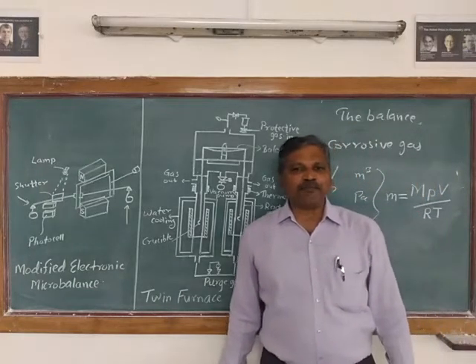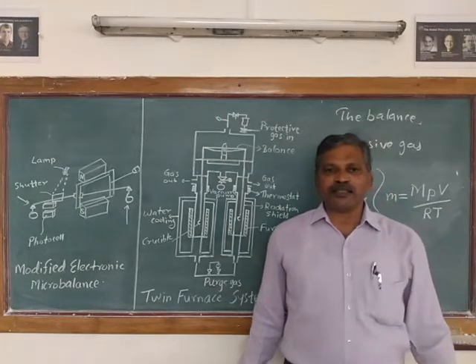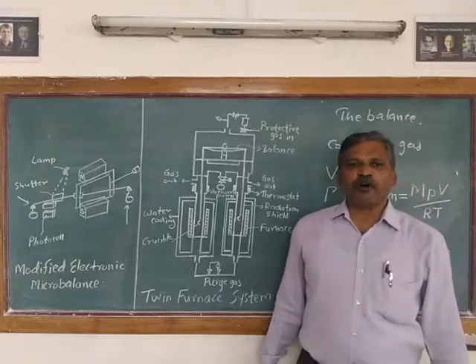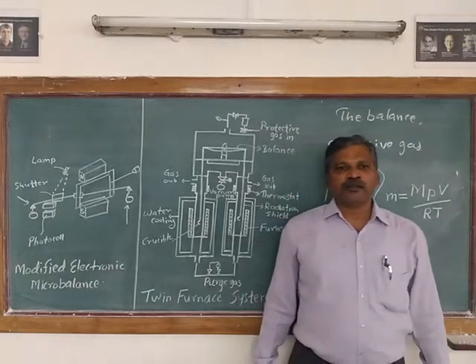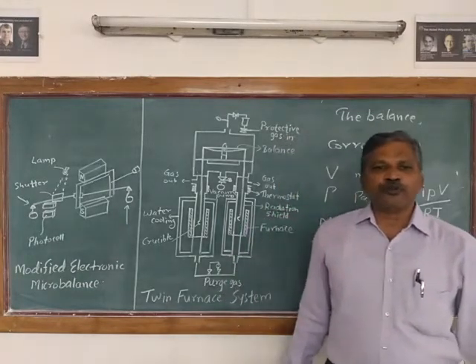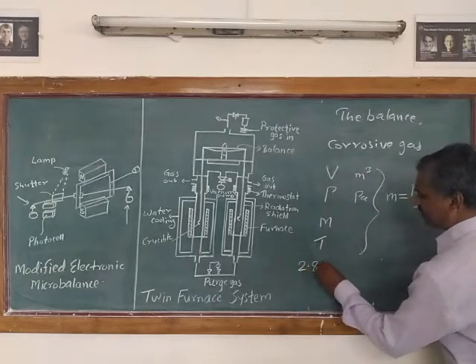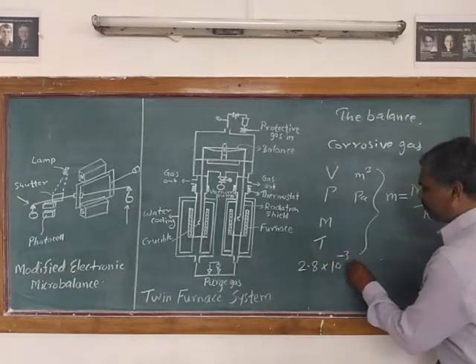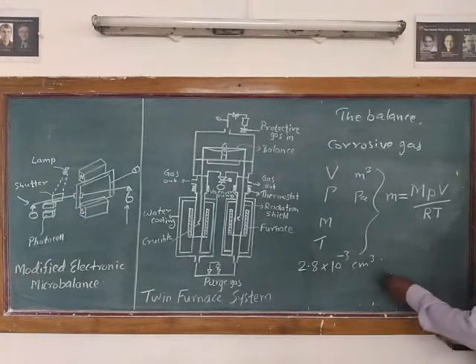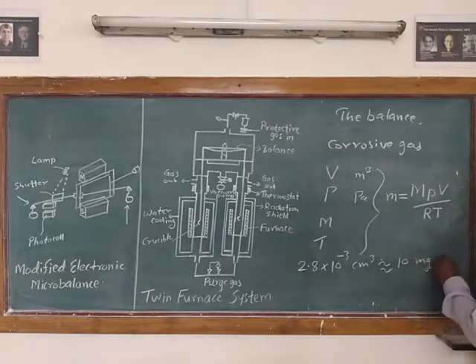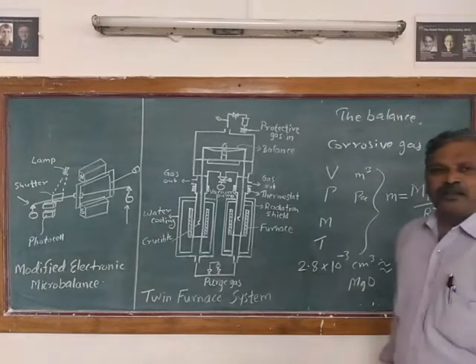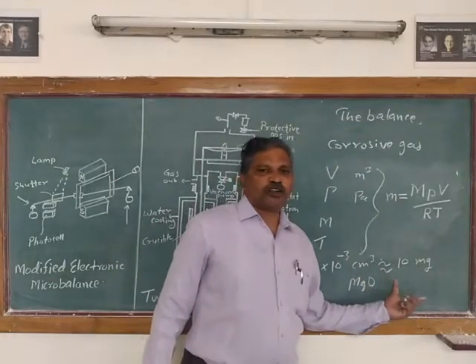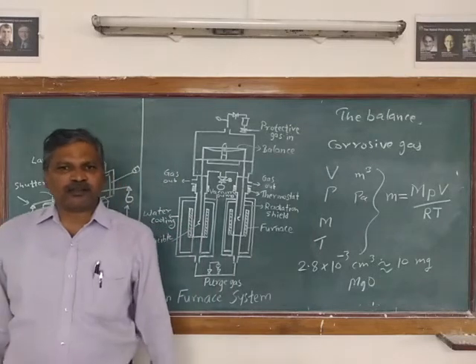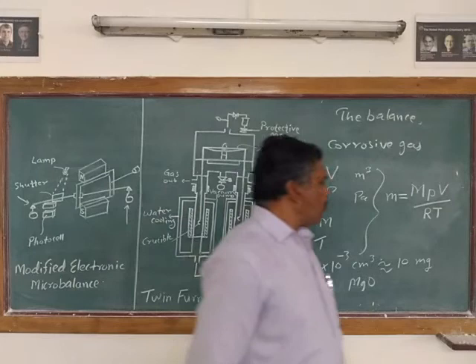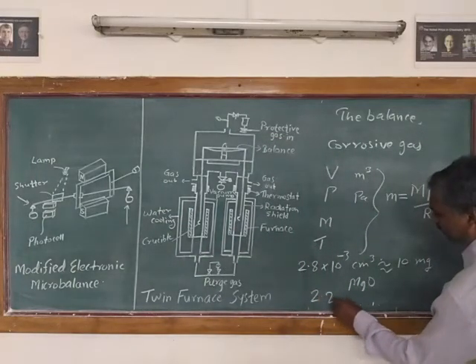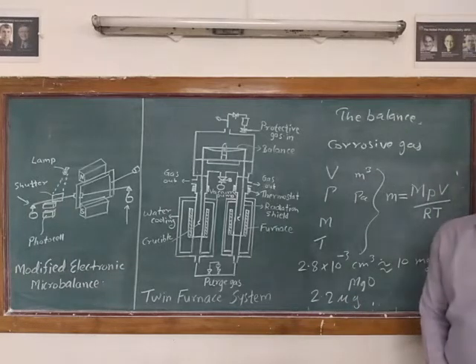Secondly, the use of very small samples and crucibles will reduce the effect. So the gain in the mass will be very small if you are using small volumes or a small amount of sample and crucible. For example, 2.8 into 10 raised to minus 3 cm cube is the volume of magnesium oxide that is equivalent to about 10 milligrams of MgO. If you carry out thermogravimetric analysis on that sample, then there is an apparent gain of only 2.2 microgram. So only 2.2 microgram of weight will be gained by the sample.